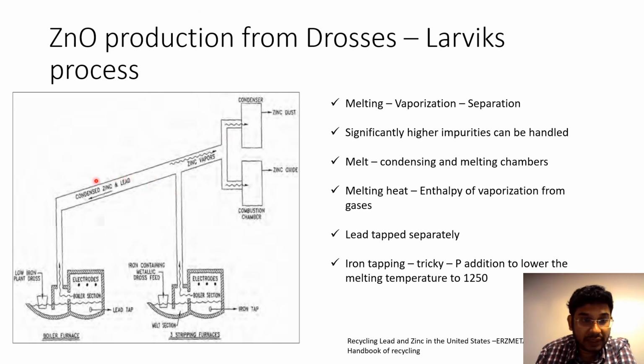Then you have the possibility that the lead goes here and then it can be condensed and collected here at one end. Or what they do also is that you have a different melting temperature set here at around 1250, because lead and zinc melt at quite low temperatures. But they have a different temperature set to here, and then they add phosphorus. Then they sort of form a Fe-P alloy, which can be melted and tapped at this particular junction. So you have the iron tap. So that's the only trick that is being played here.